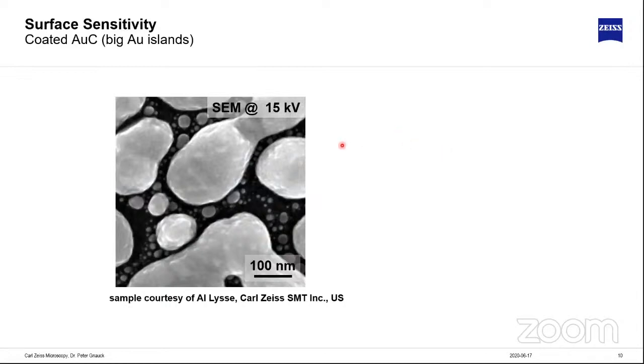If you buy an expensive field emission SEM, the first sample that you would probably put in is gold on carbon, and you would look for the sharpness of these edges. So this is an SEM image, 15 kV, gold on carbon, and I would say this looks brilliant, wonderful resolution, everything fine. Now I can tell you we have some carbon contamination on the surface of these gold grains.